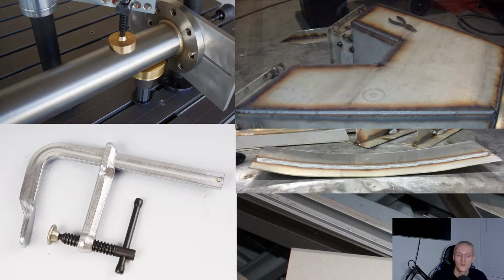You can also weld stainless steel with FCAW, but there are many cons to that. Some of those cons would be risk of slag inclusions, and it's not going to be as strong as a TIG weld normally would be. And you would need to run it on electrode positive, but some of the cheaper machines only run DCEN.